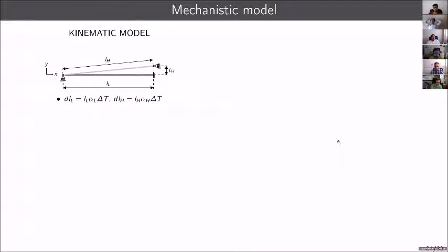We wanted to understand more what's going on with these systems, and we wanted to develop an easy-to-use, easy-to-understand model. Typically, these systems are modeled with pure kinematics, where this is a quarter of the cell that we built. What people typically assume is that there is an expansion of the low CTE bar, and there is also going to be an expansion of the high CTE bar, which is going to be larger because it has a larger coefficient of thermal expansion.